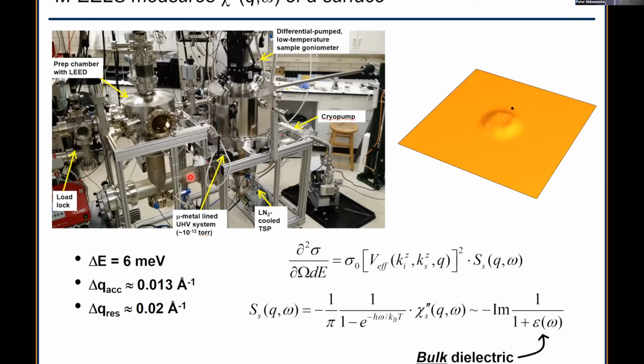So the technique is called surface electron energy loss. What's new is we've put a lot of energy into making it momentum resolved. So we call it M-EELS. It measures the density response of a surface. And this is basically what happens. You shoot an electron at the surface and it scatters off a collective mode. The energy resolution of this technique is a few milli-eV, and the momentum resolution is a few hundredths of an inverse angstrom. So the kinematics are similar to angle-resolved photoemission or neutron scattering in the resolutions.